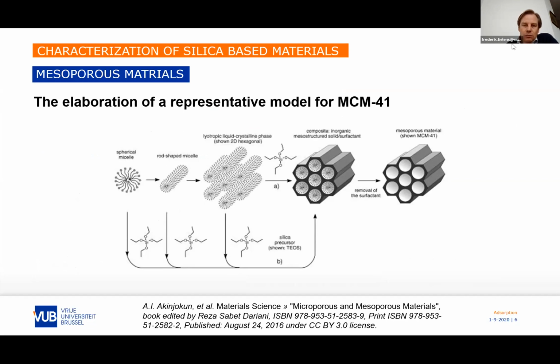Here I show you how an MCM, a mesoporous silica, is synthesized. It starts from an assembly of surfactants. You have kind of micelles which make those rods. They assemble in a hexagonal symmetry, and around this structure of surfactants, you can grow a silica framework. You burn out the organic material and you are left with what you see here, this hexagonal symmetry structure with these channels. So the idea is to make a model for this.